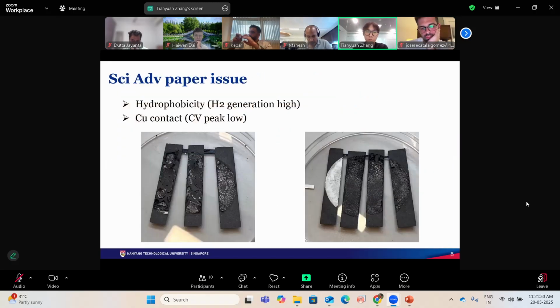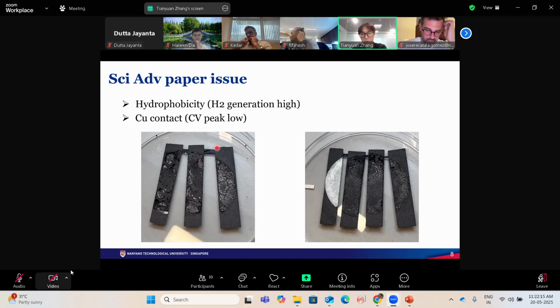But we still found two issues in this Science Advances paper. The first one is the hydrophobicity. We found that after we do the carbon thermal shock, the cellulose will shrink, and it will lead to a lot of empty space, which allows the water to go through, and hydrogen will be generated, which is bad for CO2 product generation in CO2 reduction reaction catalysis.